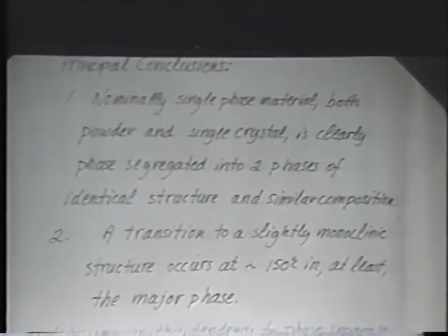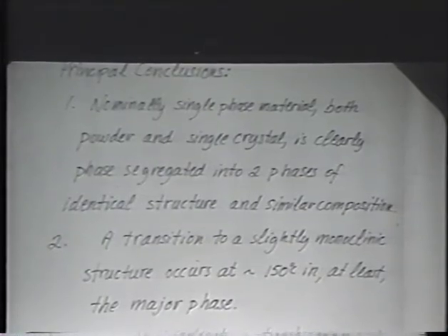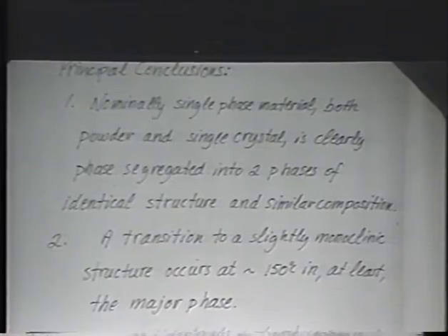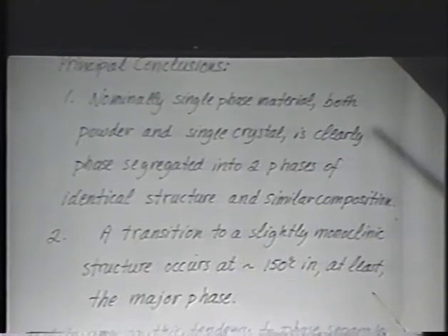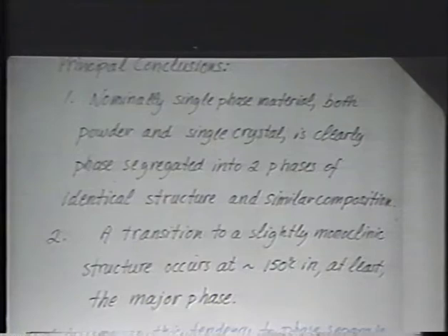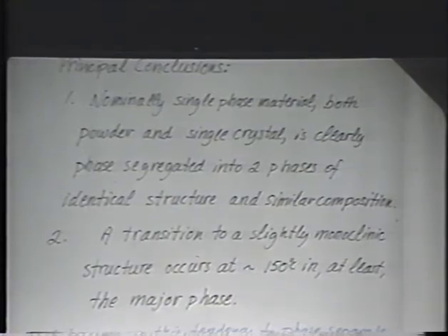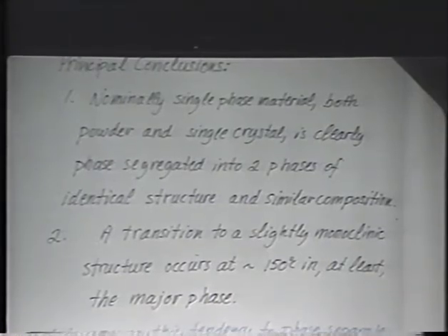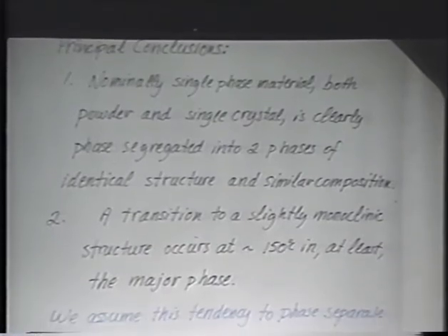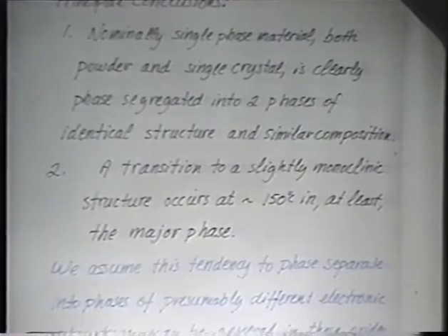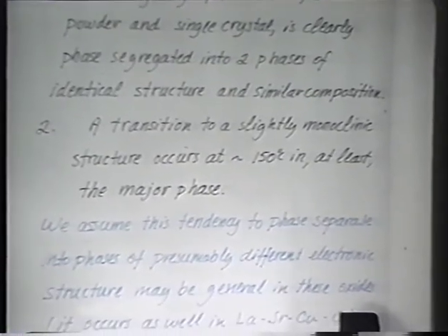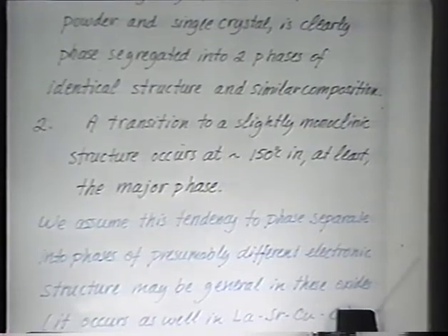The principal conclusions are that we have a nominally single-phase material, which would be identified as a single-phase material in a normal diffraction experiment. One could push a rotating anode with double monochromators to give you much better resolution than that. But in a normal diffraction experiment, it would be nominally single-phase. But both the powder and 70-micron single crystal data that we collected show clear evidence of phase segregation into two phases of identical structure and similar composition. And secondly, we see a transition to a slightly monoclinic structure occurring at around 150 degrees in at least the major of those two phases. And that assignment of monoclinic we believe to be a minimum assignment.